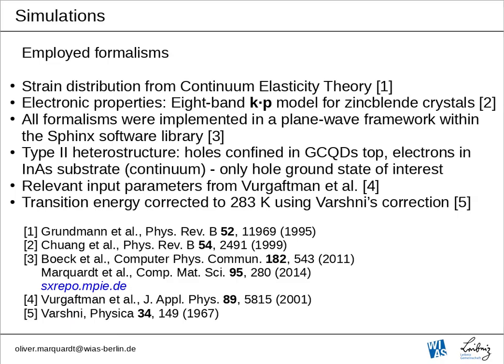Let me mention that the system we are talking about is a type 2 heterostructure. The holes can be expected to be confined somewhere in the graded composition quantum dots, whereas the electrons will be in the indium arsenide substrate on a continuum energy level. So only the hole states, or even the hole ground state, were of interest for us. All relevant input parameters were taken from Vurgaftman's paper, which is pretty much the standard for such simulations. As these parameters are designed for 0 K calculations, we had to correct the energies to 283 Kelvin using Varshni's correction.